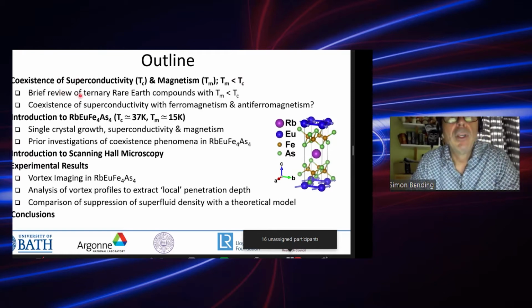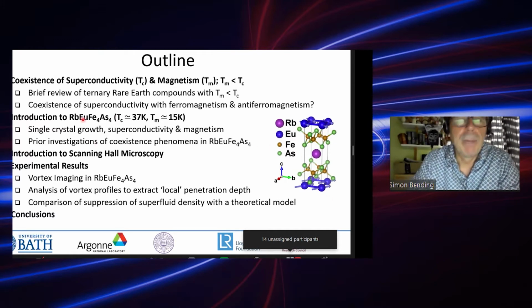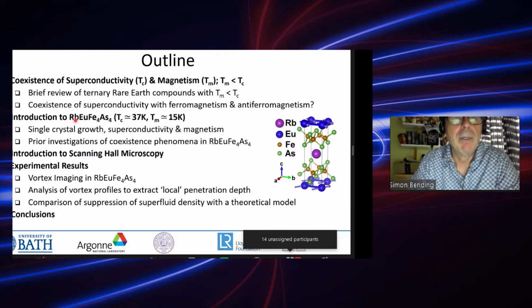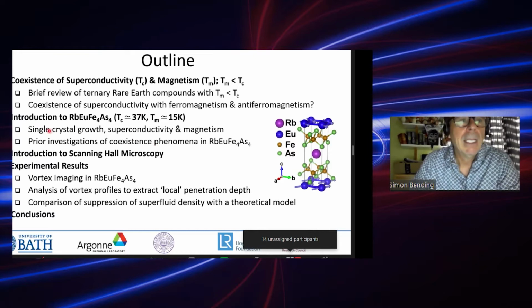I'll give a very brief review of ternary rare earth compounds which were studied in the 70s and 80s, which fall into this limit, and talk about some more general considerations of the coexistence of superconductivity with both ferromagnetism and antiferromagnetism. So the material we're interested in today, here I show you a unit cell. It's a fairly complex material with 4 elements in it: rubidium, europium, iron, arsenide. It has a superconducting critical temperature of about 37 Kelvin and a magnetic ordering temperature of 15 Kelvin. So that's well below the superconducting temperature.